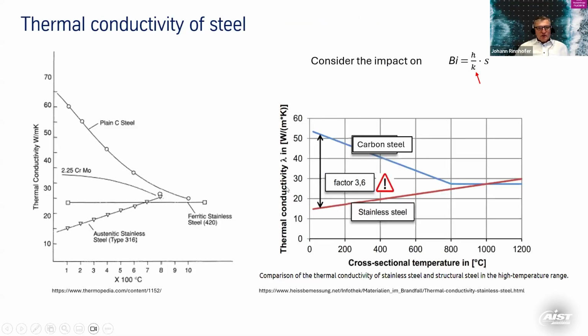When we look at this Biot number, we now talk about the heat conductivity, which is shown here. What is the thermal conductivity of steel? You can see normal carbon steel comes down from the area of 50 watts per meter Kelvin and goes down to around 28 or so in the area of 800 degrees. So it's around the Curie temperature of 770 degrees. And stainless steel, or some austenitic stainless steel types, come from the complete other end. They start at 15 watts per meter Kelvin, and they also go to this area of 28 in the area of 800 degrees or so.